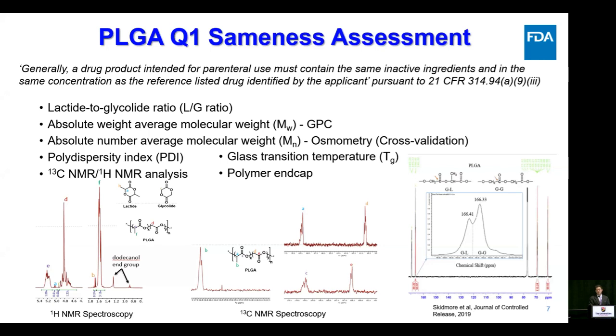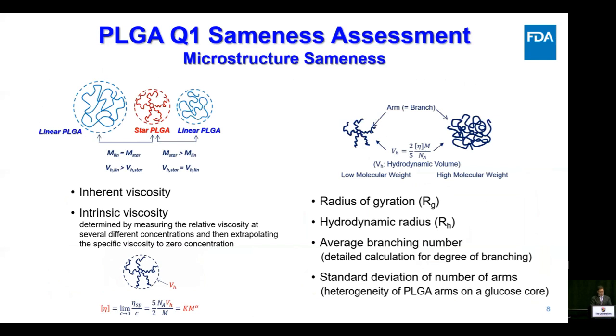And also PLGA is a sort of polymeric material. And so as in the general polymer science evaluation, we need weight average molecular weight and number average molecular weight with polydispersity index, and also glass transition temperature and viscosities. There are two kinds of viscosities. One is inherent viscosity. The other is intrinsic viscosity. Intrinsic viscosity is determined by measuring the relative viscosity at several different concentrations and then extrapolating the specific viscosity to zero concentration.